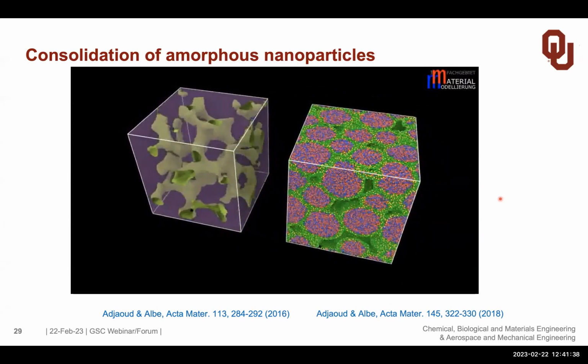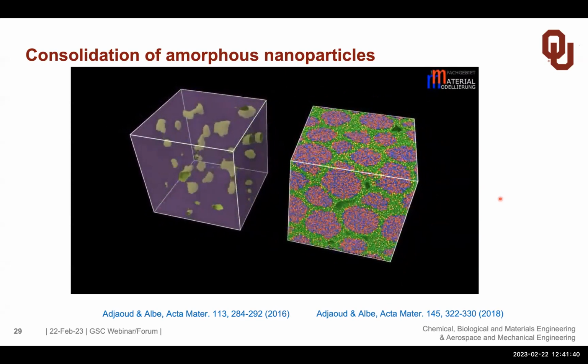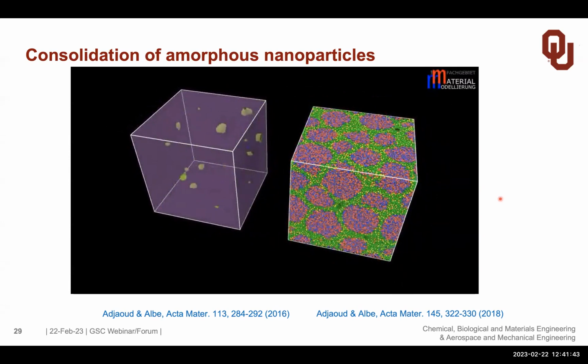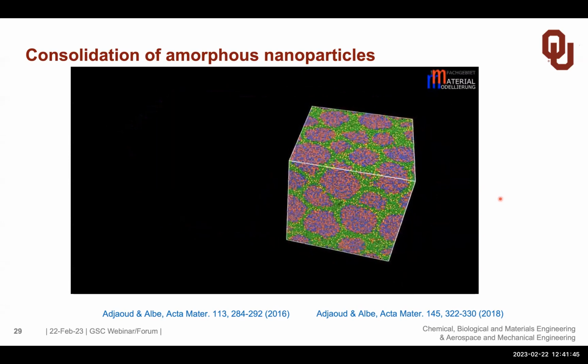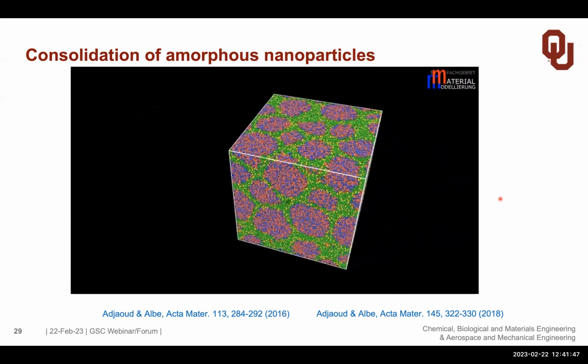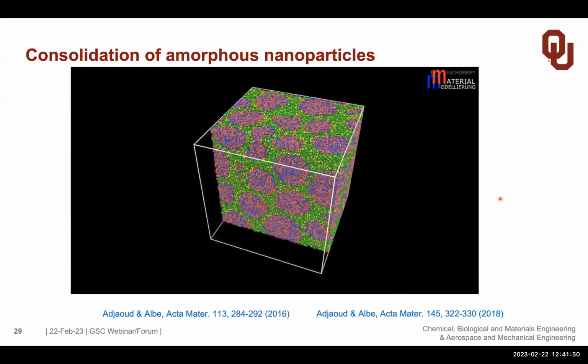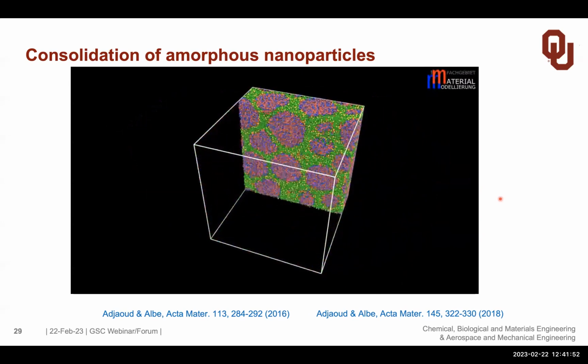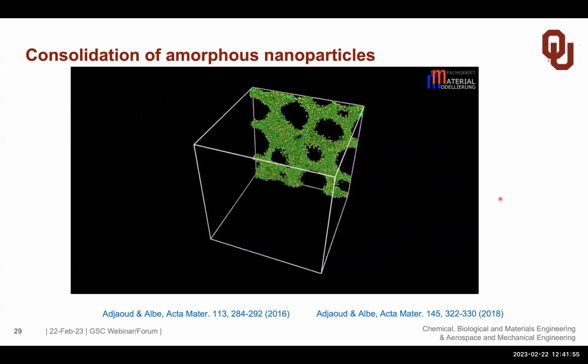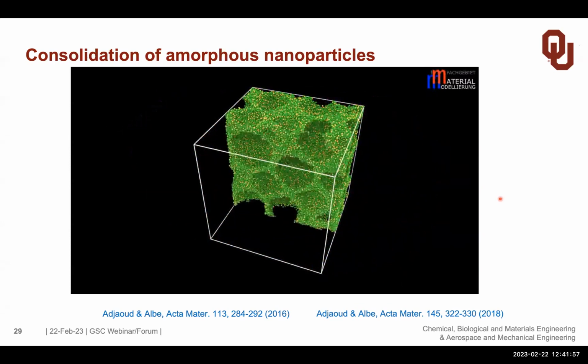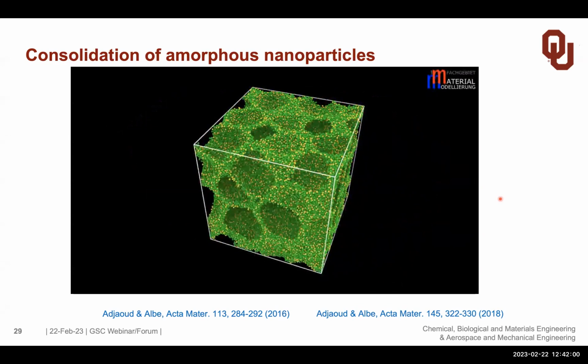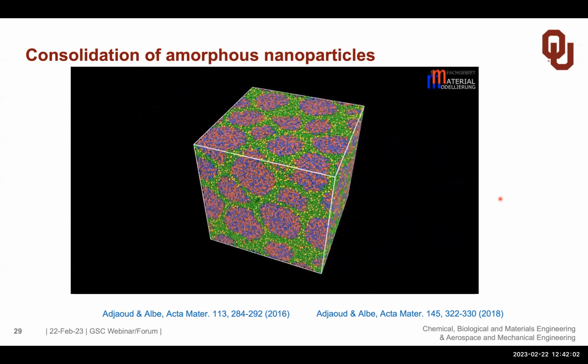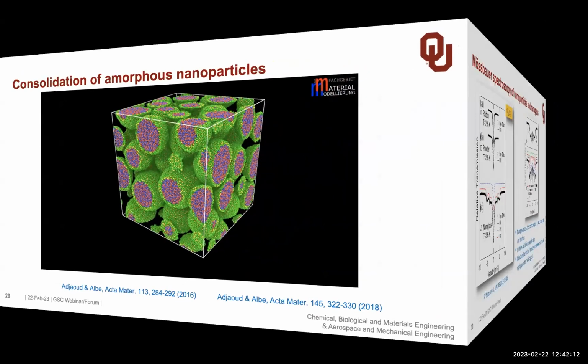So now we compact it, and we get rid of the porosity between the particles, which we have initially. And eventually we have a non-porous, a pore-free material, which you can now analyze because you know all the positions of the atoms in this simulation. And these are, the green is the interfaces, and now this is a cores and so on. So you see, it's an interesting approach to a material synthesis in order to get a different structure.